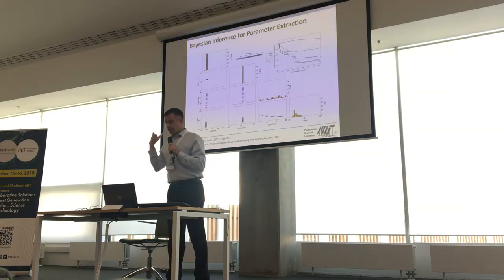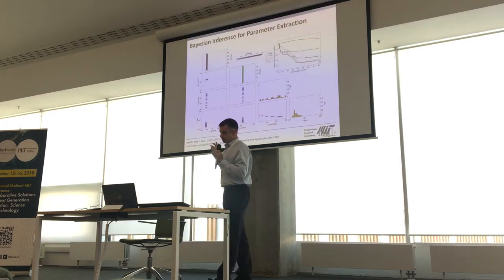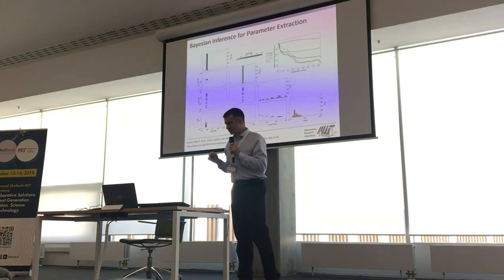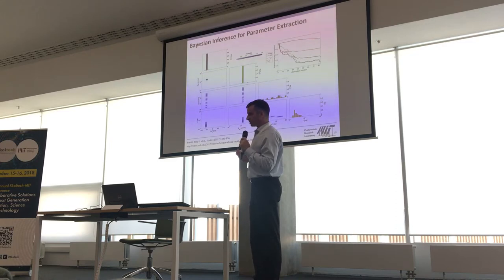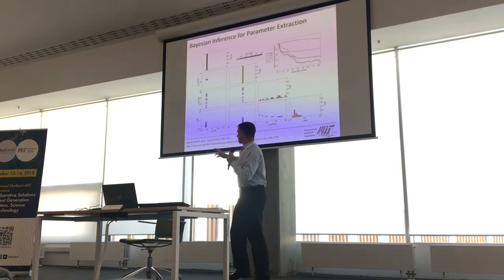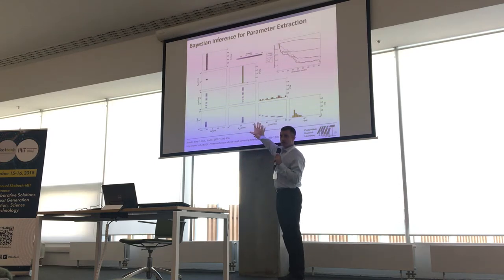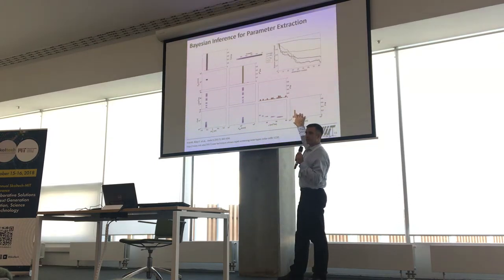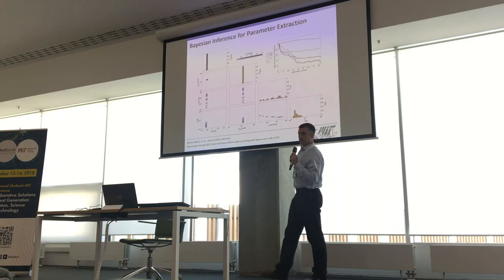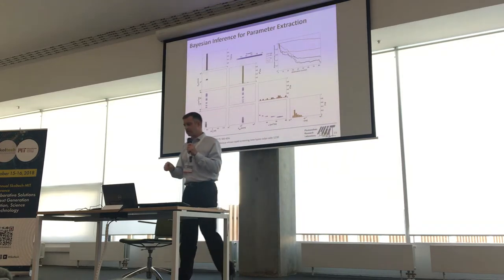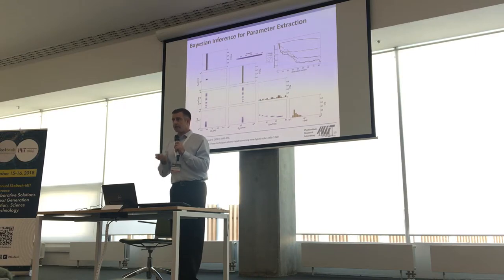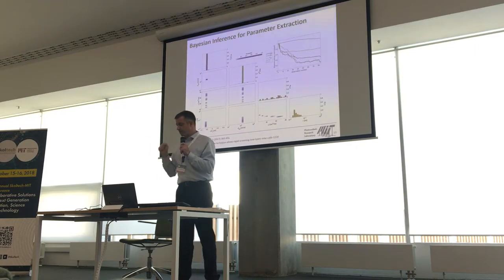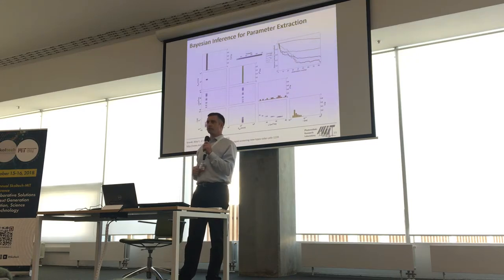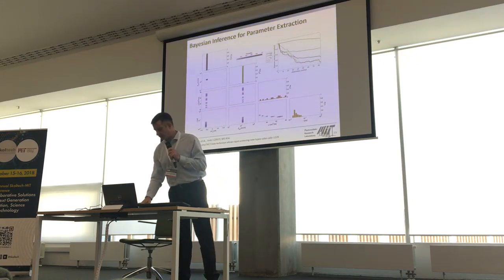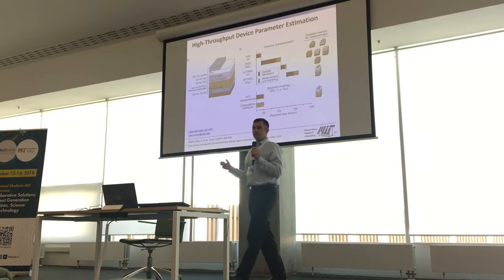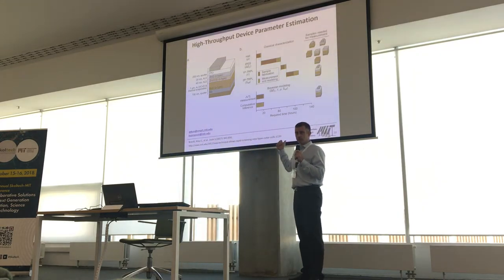And when we plug these PDFs, probability distribution functions, or more precisely probability mass functions, into a forward model, into a solar cell device simulator, we find that these three variables are not limiting solar cell performance, but this one over here is limiting our solar cell device performance. In other words, you can transform this into a sensitivity analysis and determine the variable that impacts device performance. So what this allows you to do is pinpoint with precision what you have to improve in your next round of solar cell fabrication. And in terms of time, it takes about 1/10 the time of traditional spectroscopy.